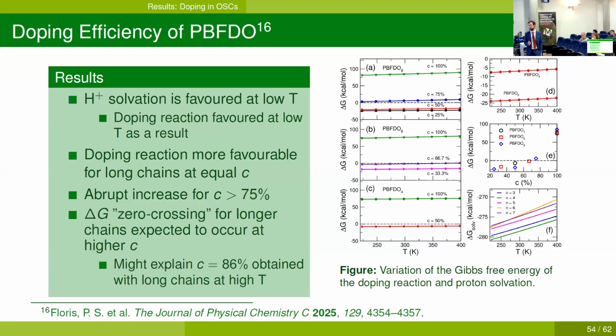These two things together lead us to expect that the delta G zero crossing for longer chains might be expected to occur at higher concentration. By zero crossing, I mean the value of the concentration for which the delta G becomes positive. These two things together might explain how in the literature an experimental doping efficiency of 86% was obtained with long chains despite conducting the reaction at high temperature.